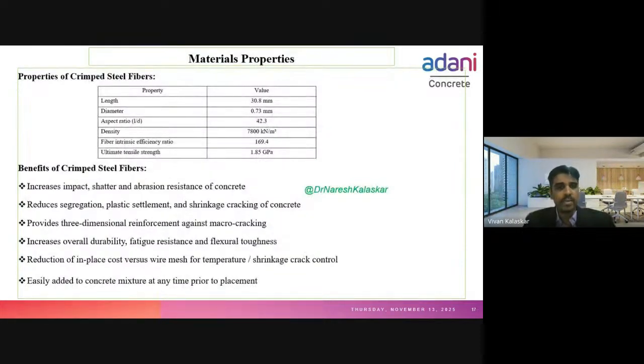Crimped steel fibers. The crimped steel fibers density is 7,800 Newton per meter cube. And the aspect ratio is one of the important points in UHPC for fibers. The aspect ratio which we have used in this design is 42.3. Its aspect ratio is nothing but L by D, length and diameter of the fiber.